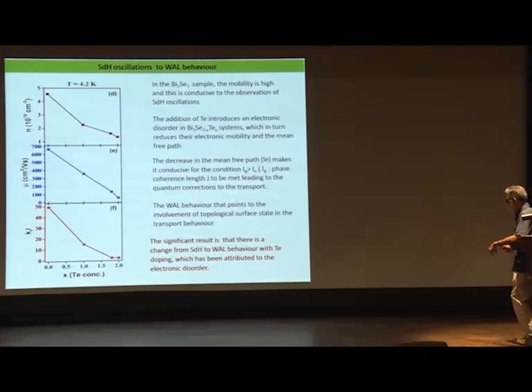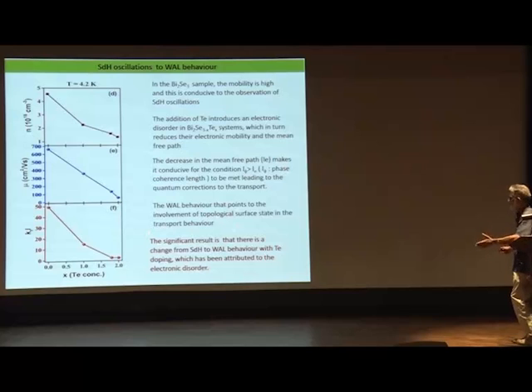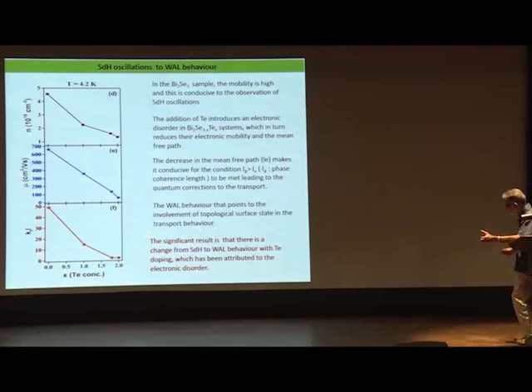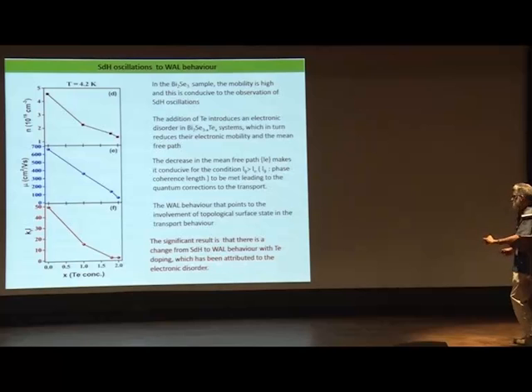The weak localization behavior again points to the involvement of a topological surface state in the transport. The significant result is a change from SDH oscillations to weak localization behavior with tellurium doping, attributed to electronic disorder.